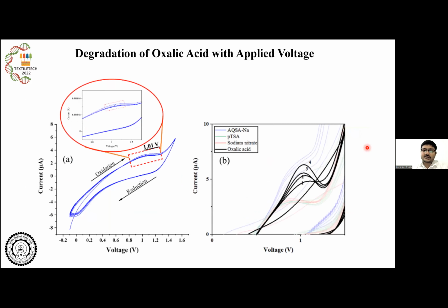In case of oxalic acid, it was found that the oxidation potential of oxalic acid is 1.01 volts, which is very close to the oxidation potential of our monomer, around 0.7 volts. So as the polymer is formed, this oxalic acid starts decomposing and forms carbon dioxide and then leaves the system. So it is not a good dopant for our work.